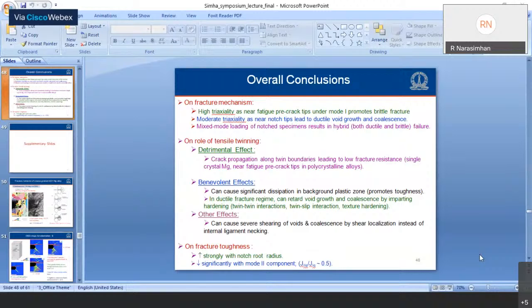There's one question from Sukrit. Do you think the slip mechanism would help absorb energy if used as a front crash beam in a passenger vehicle? Yeah, see, the thing is, slip is always present. And if you look at magnesium, this is a difficult question to answer because, as I showed in my slide right at the beginning, the CRSS values for different slip systems vary very vastly. If you look at magnesium single crystals, the CRSS for basal slip is as low as 0.5 MPa. On the other hand, if you take pyramidal c+a, it's much higher. So it depends on